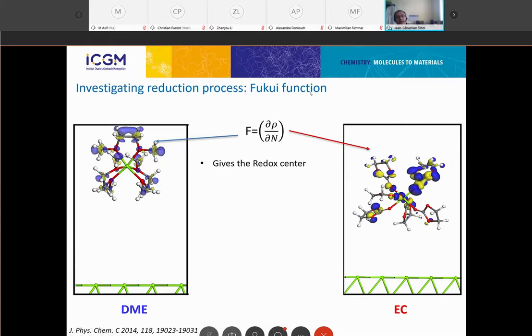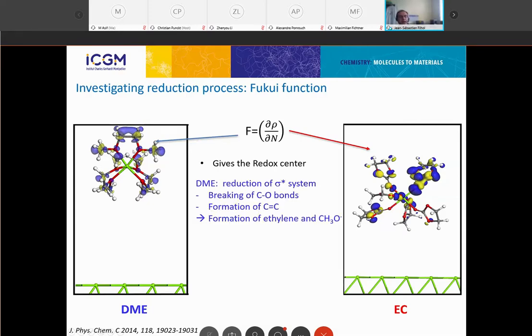This can be given by the Fukui function. The Fukui function is some kind of mathematical tool, but that gives you the chemical ID of reduction center. When we compute it, it gives us where the electron flows from the electrode. So when I just add an electron to this molecule, I directly see that in the DME case, I'm getting some kind of sigma star system reduction that will lead to CO bond breaking and the formation, you see it there, of some kind of C double bond, and that tells you that's going to lead to the formation of ethylene and methanol.